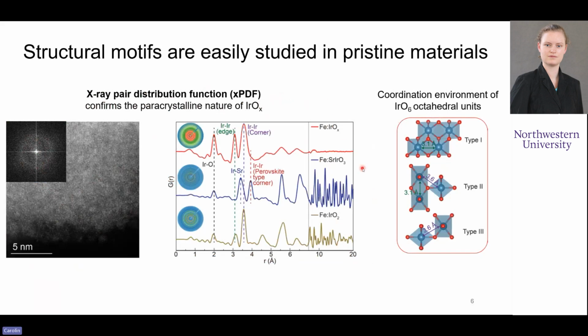And so we have from the bottom to the top here, this is just the rutile iridium oxide. And you can see this is a bulk crystal, so you can see crystalline features all the way in the really far radial distances. And the same is true for the strontium iridate perovskite. Both of these are bulk crystals. And then when you look at our almost paracrystalline iridium oxide, you see it has short range order, right? We have very specific motifs that are present up to like 9 angstroms of distance. And after that, you have no more order that's present in this material.